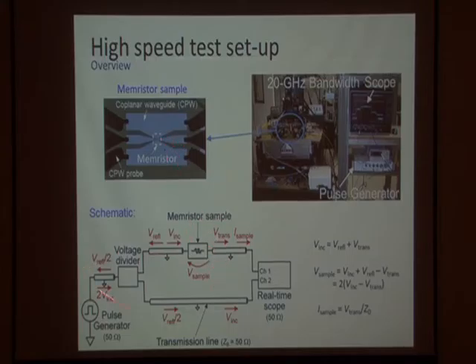This is the thing that Antonio is really good at. Even though there's a little bit of reflection, he was able to do some impedance matching. Moreover, the time that it takes for the pulse to hit the sample is finite because we're working really fast. So you can actually measure the reflection and the transmission. It's almost like a 4-probe type experiment, but you do that in time. You send the pulse, and then you know what went through and how much was incident, and you can track all those in the oscilloscope.